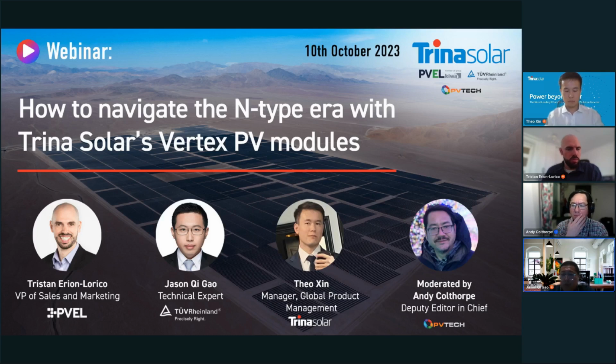However, for some TOPCon modules, the metastability can be seen even after several seconds of the light soaking. So for some TOPCon modules, it is more sensitive. And now there is no related evaluation method for metastability in the IEC standard. In our lab, we will take two measurements, before and after the light soaking or current injection, for this kind of modules. But how to use this kind of module as a reference module in the production line is still challenging. I think the PV manufacturers need to take these issues seriously.